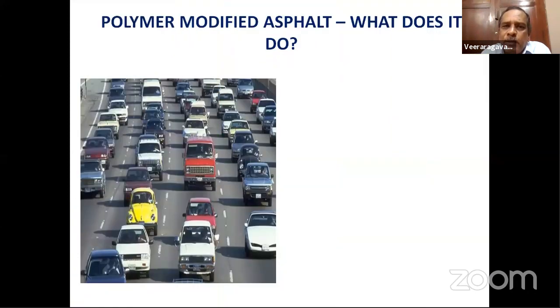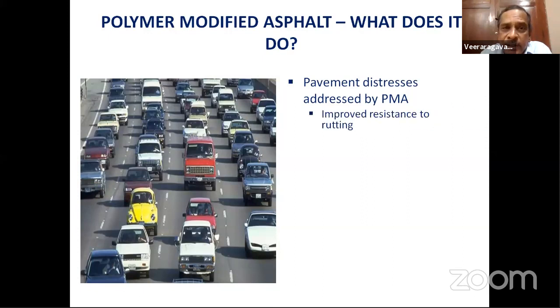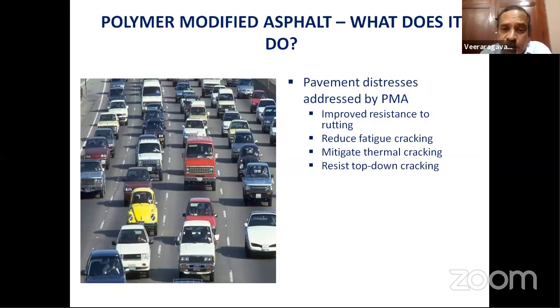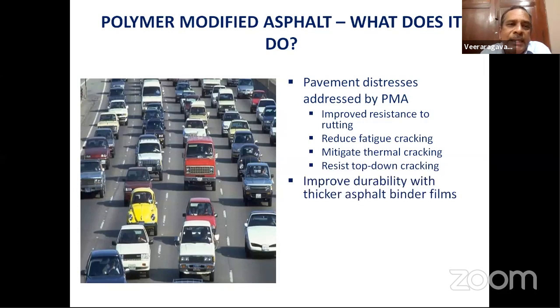When you use this polymer modified binder, it addresses the majority of the distresses occurring on the prior unmodified asphalt. They offer an improved resistance to rutting. They have reduced fatigue cracking. They mitigate thermal cracking. They resist top-down cracking and improve the durability with a thicker asphalt binder film, higher asphalt content and reduced moisture damage. So in a nutshell, provision of a modified asphalt will improve the life of the pavement. There is no doubt about that.